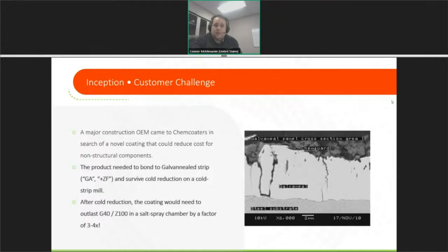And then at some point we got to work and came up with a coating that did just that. Now, I showed this picture a second time, and the reason I show it a second time is to comment that this SEM photo is actually our coating post-cold reduction. So the strip in question here will have been elongated probably through a few passes, 30, 40, 50%. So our customers have really been able to increase linear footage, piece count, and value just by adding a relatively inexpensive coating back onto secondary steel. I spent about 10 years at a major steel mill in Europe and in various different regions, and I did not believe before coming here that such a process was possible, let alone productive, and it has been one of my great surprises to see how strong this product is. Next slide, please.